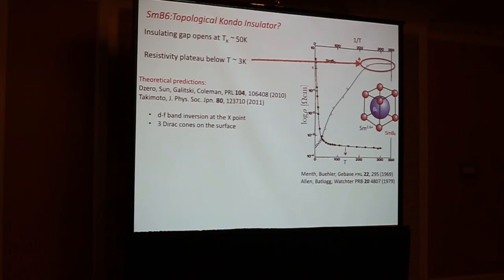And once we learned the simple trick from Fu and Kane of how to calculate whether you have a twisted topological ground state, we realized that we could use this to analyze samarium hexaboride. And after we made our proposal, Takimoto came and worked out the detailed band structure of the problem. The basic idea is that if there's a d-f band inversion in this system, it occurs at 3 points, at the X point. Since it occurs 3 times, you should get a strong topological insulator with 3 Dirac cones on the surface.